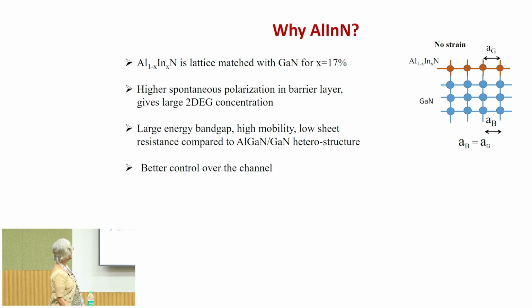So these are basically the two advantages of aluminum indium nitride, and it allows us to go for a much thinner barrier layer, and therefore, we can actually get much higher transconductance also. So, we can have much higher current drive, much higher transconductance compared to the aluminum gallium nitride heterostructure.